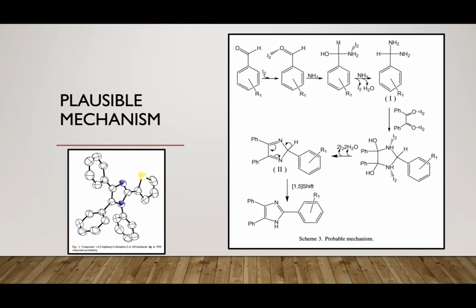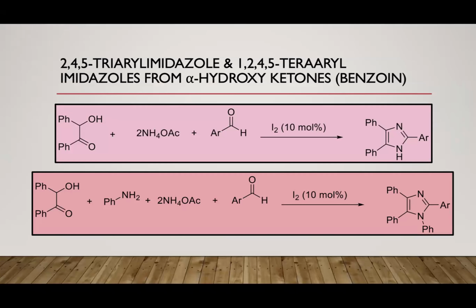After getting good results with 1,2-diketone, we tried the synthesis using alpha hydroxyketones. Instead of 1,2-diketone, we replaced it with alpha hydroxyketone. There are several papers reported in the literature using 1,2-diketone, but very few papers using alpha hydroxyketone. So we took benzoin. Note here that 1,2-diketones like benzil are usually prepared from benzoin. So if we are using alpha hydroxyketone, we have removed that extra step which is required. Consequently, this is a significant improvement in terms of green chemistry.